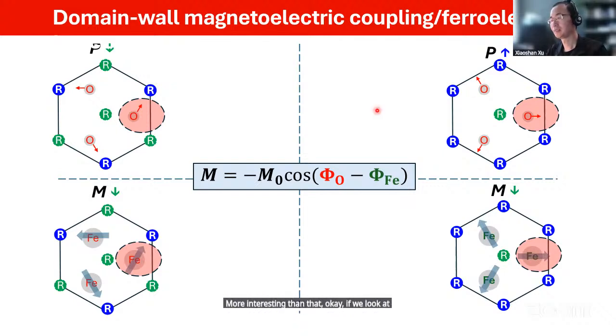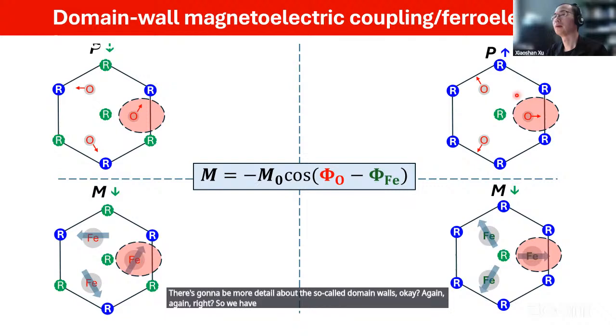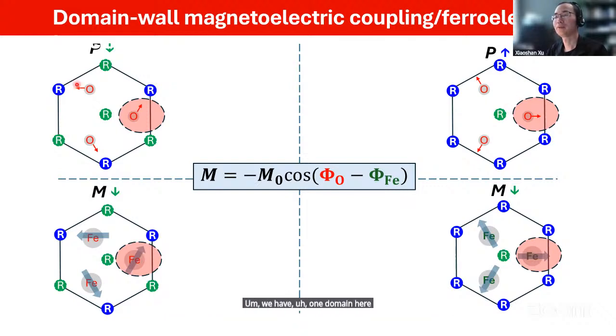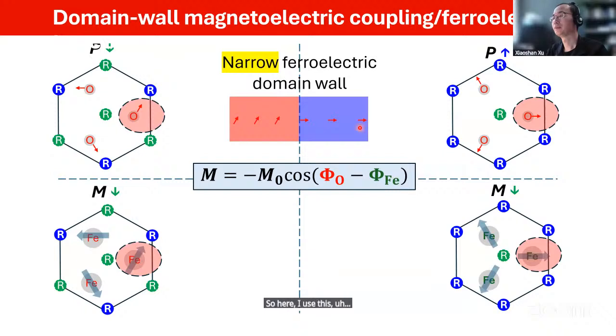If we look in a little more detail at the so-called domain walls. Again, we have one domain here, we have another domain here. Now let's look at the domain wall. Here I use this arrow to represent the oxygen displacement. On the right-hand side, they all point to the right. On the left-hand side, in this domain, they point at this angle. One thing we all know is that the ferroelectric domain wall is very narrow. It's almost atomic size because it has to do with structure. So you almost have an abrupt change of this arrow.